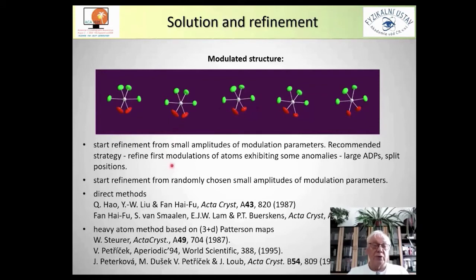After having this average structure, we could start refinement with small amplitudes of modulation parameters. The recommended strategy was to refine first the modulation of atoms exhibiting some anomalies like large ADPs and split positions. Another possibility is to start refinement several times with randomly chosen small amplitudes of modulation parameters. But also some very specific direct methods were developed by Professor van Smaalen, and were used to solve several structures. Another alternative was to use the heavy atom method based on the Patterson function, used by Walter Steurer and also in our group. This method was just taking one particular Patterson peak and making some more detailed analysis of the Patterson peak in four-dimensional space.